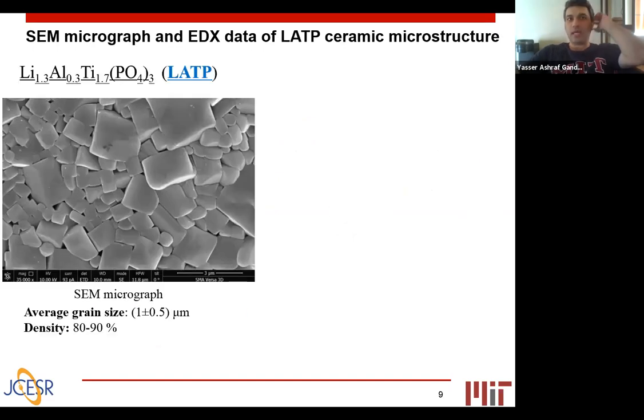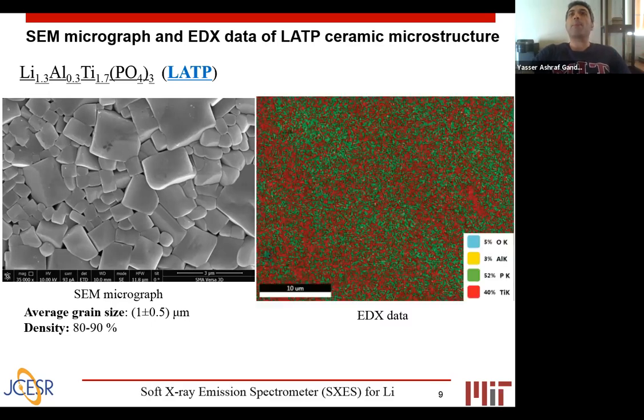Looking under the SEM, average grain size was about 1 micrometer with a density of 80 to 90%. And analyzing the EDX data, we could confirm the elemental composition of the LATP structure, including oxygen, aluminum, phosphorus, and titanium.